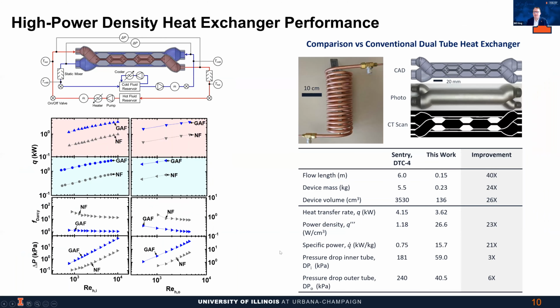Okay, so we tested these devices. They performed very well. The heat transfer rates are around 10 times higher for the fin devices compared to no fin devices.